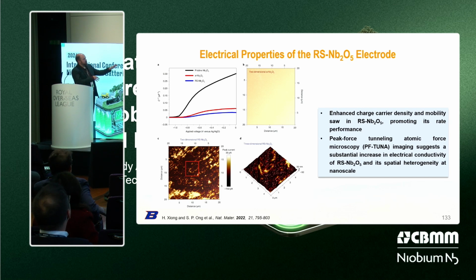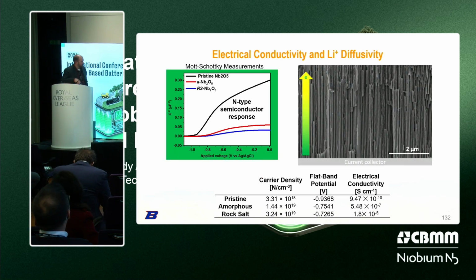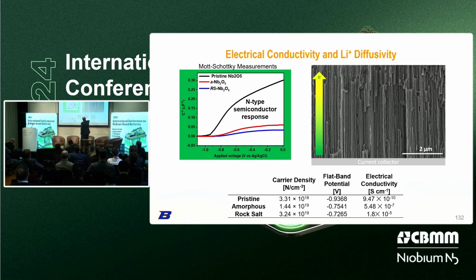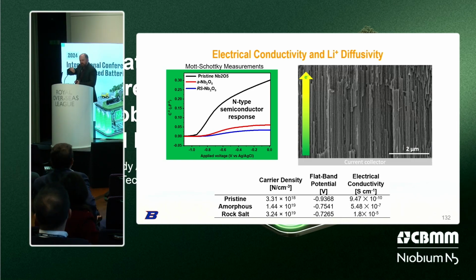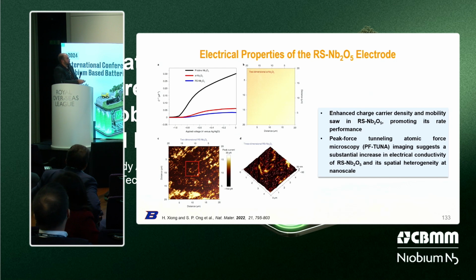At the same time, what you're seeing here is atomic force microscopy using peak force TUNA. So you're seeing tunneling, electrons tunneling through the oxide. If we go back and look at it, the AFM is coming from the top, and you're having a current supplied at the bottom. As the tip of the AFM comes closer, those electrons can come through depending on the current being pushed through and the voltage applied across it. In the comparison here, the AFM tip pretty much saw nothing at those currents, so we had to go through iterations of voltages on the other side of the material. This is in a glove box AFM. And with the rock salt one, when the tip gets close enough, the electron shoots through.